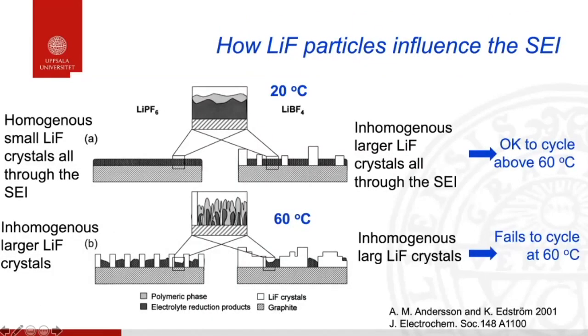We started early, and I think sometimes you can actually go back. So much is published in this area that if you go back a little bit in the literature, you might find that we did things before. This is an example of a model system where you compare just the salt LiPF6 in the same kind of solvent as LiBF4 at room temperature. With LiPF6, you get a really nice smooth layer of very small crystalline lithium fluoride. You get a bit larger, chunky ones for LiBF4.